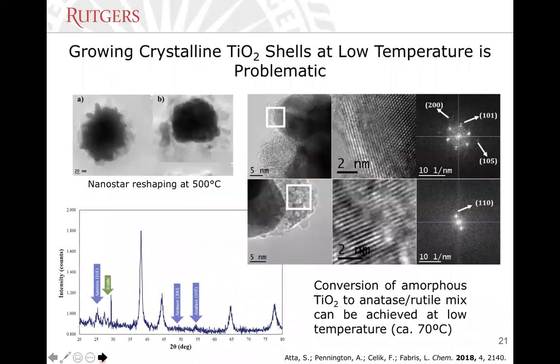So if you have ever tried to coat gold nanostars with crystalline TiO2, you know that you cannot do it the normal way. If you try to use sol-gel protocols to coat nanostars with TiO2, then you're going to get amorphous TiO2. We need to recrystallize it with calcination at 200 to 500 degrees C. But if you do that, you will get crystalline TiO2, but you will completely reshape the nanostar. These nanostars start to reshape above 85 degrees C. So there you go, our limit is 85 degrees C. So we had to figure out a way to reduce the synthesis temperature to below 85 degrees C.